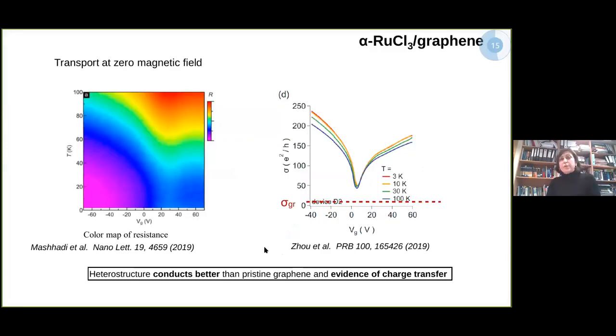Their measurements show the following. Here are the measurements from Stuttgart, and here are the measurements by Hendriks and collaborators. Basically, they reproduce the same results. What we see here is a color map of the resistance, and you see that it is unequal whether the voltage is negative or positive, which tells us that we do have holes doing the transport in graphene, and that the conduction improves because of this charge transfer to the insulating lattice. So this confirms the prediction.